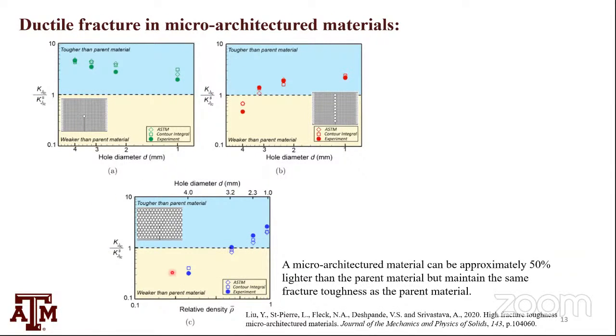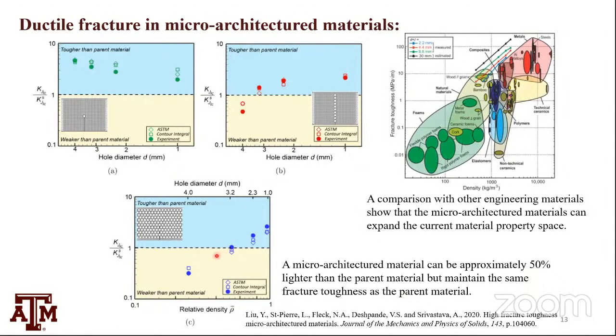In the microarchitecture material, we get a nice comparison with experiment as well, actually slightly better than what we got in single holes. And we showed nicely that with this microstructure-based modeling, we could design lattice or architected materials that are 50% lighter than the parent material but maintain the same fracture toughness. This denominator is the fracture toughness of the parent metal, which was aluminum 2000 series.